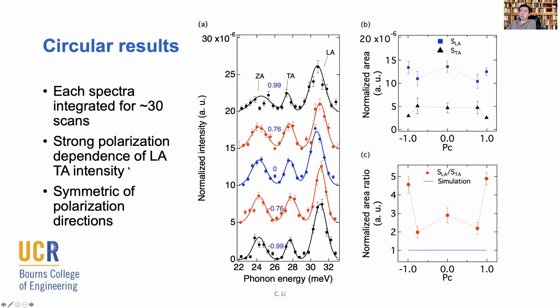Okay, so the conclusion is we see some strong polarization dependence of the LA/TA intensity. We're still statistically limited, but something is going on, and we're still trying to interpret the result, because honestly, the result is not what we were expecting. We were expecting more of a straightforward selection rule, like certain circular polarization may be able to excite certain phonon polarization more effectively than the other, but we're actually not seeing that.